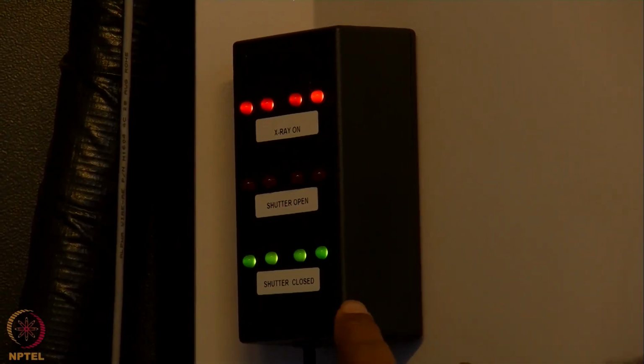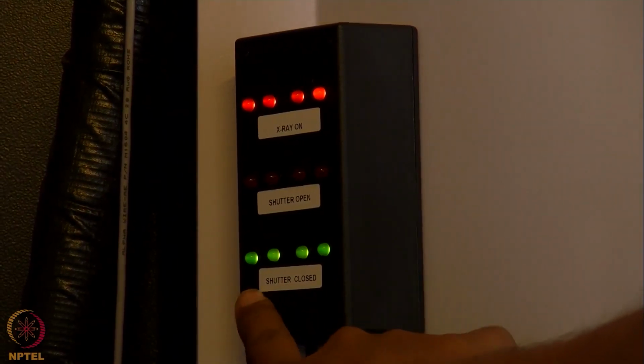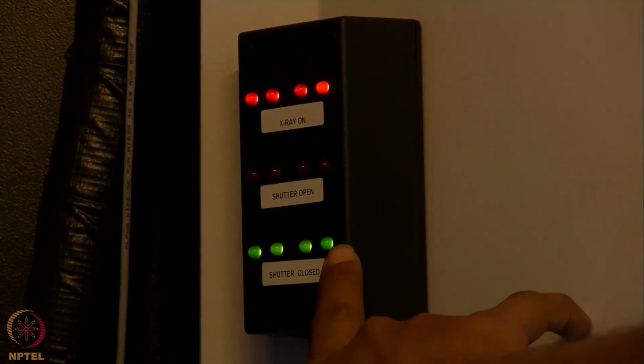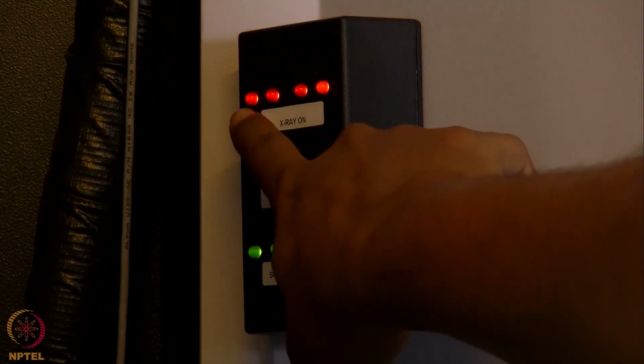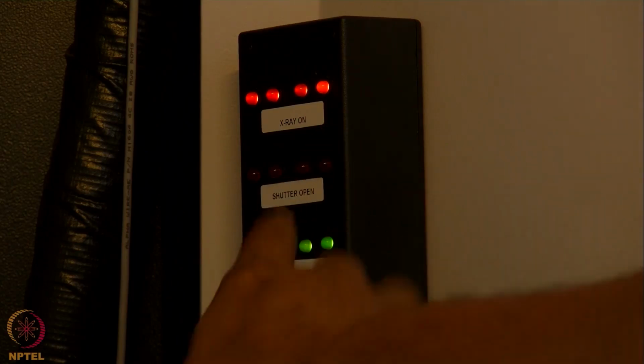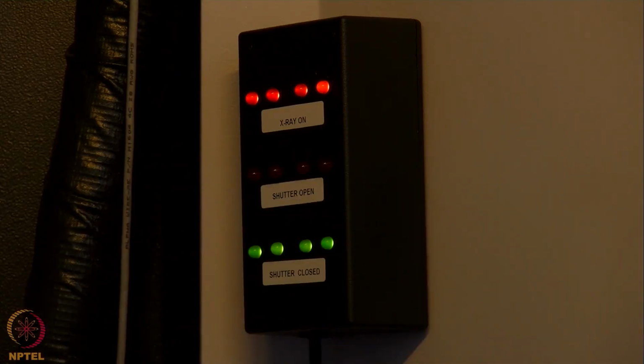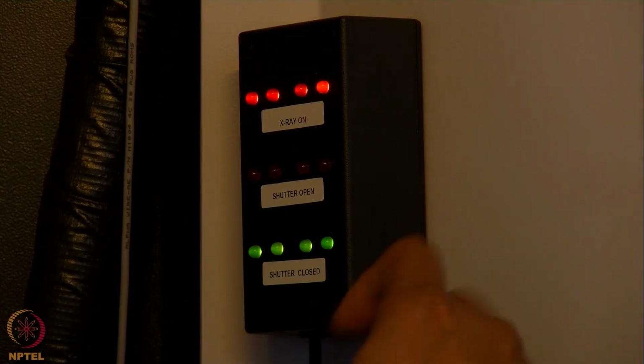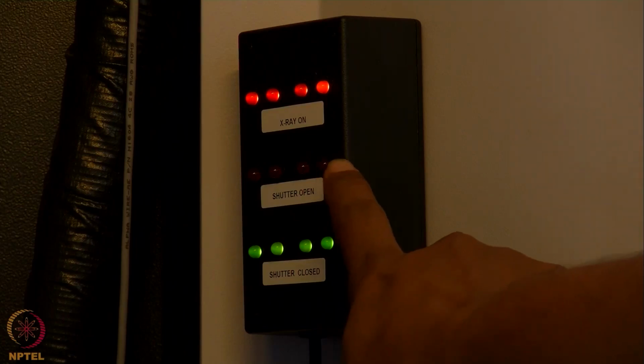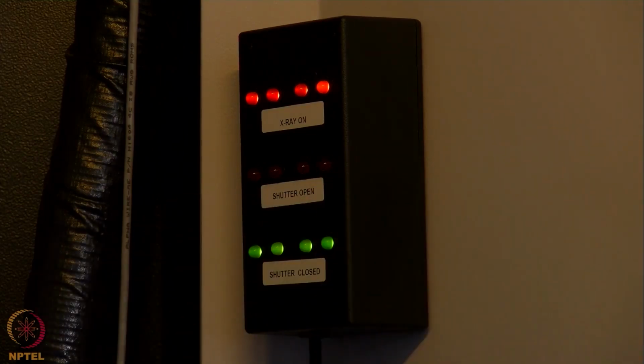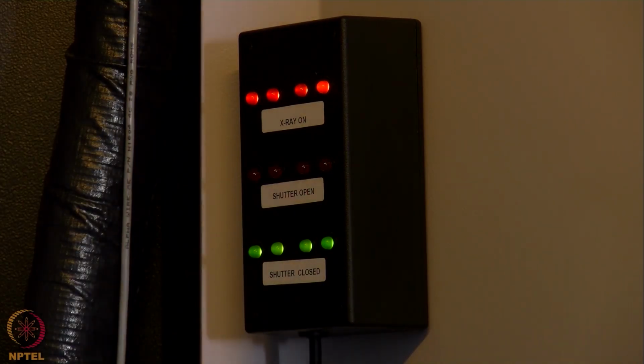This is the indicator showing that the shutter is closed, so the green lights are on. When the orange lights are on, it says X-ray on. That means the tube is on, it is generating X-ray and it is kept at the lowest voltage and current, the standby condition. And when the shutter is open, this red light will be glowing, which indicates that the X-ray is inside the chamber, so we should not open the door. Just like powder X-ray diffractometer, we won't be able to open the shutter until and unless we close the door in front of the diffractometer.